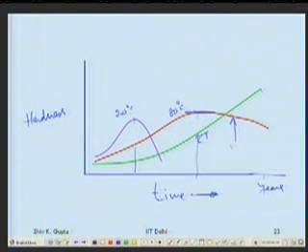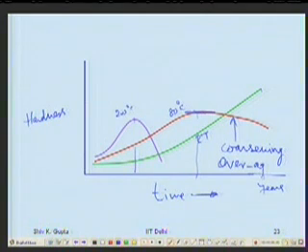Beyond that, what happens is, because of a large number of precipitate particles, I have created a large interfacial area. Interfacial area provides extra energy to the material, and the tendency is to decrease that interfacial area. That happens when the particles grow in size. So some neighboring particles dissolve and one particle grows. Coarsening of the precipitate occurs here. And this is also called overaging. This is called optimum aging.